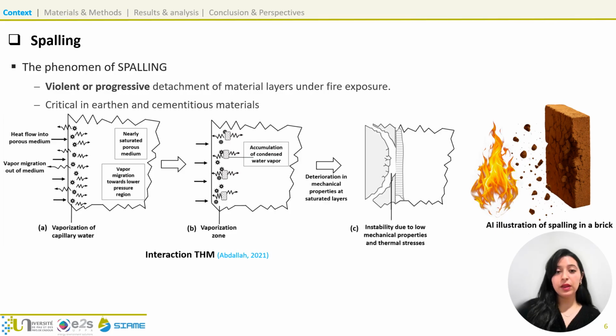One of the most critical phenomena in the fire behavior of construction materials is spalling, defined as the progressive or violent detachment of the material layers during fire exposure. In his research, Abdullah concluded that on compressed earth bricks exposed to fire, thermal instabilities can arise due to the coupling of thermal, hydraulic, and mechanical effects. As illustrated in this schematic, as the temperature increases on the heated side, the water contained in the pores begins to evaporate. Part of this water migrates toward the cooler side, where it accumulates in pores, leading to a buildup of internal pressure. At the same time, the loss and movement of water reduce the mechanical strength and cohesion of the material. Once the internal pressure exceeds the material's resistance, cracks develop and surface layers may detach, resulting in spalling. Here the spalling phenomenon is shown by an AI-generated illustration.